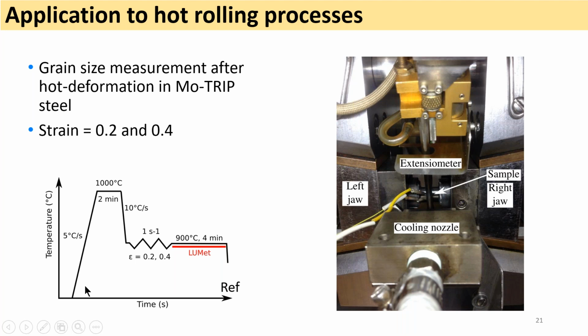This treatment consists of a sharp rise in temperature up to 1000 degrees, and then we lower the temperature to 900 degrees, apply a deformation of 20% or 40% strain, and then hold at 900 degrees for the recrystallization to occur. The picture that I show you here is the setup that we have used. There is a quenching nozzle here to quench the sample after the treatment, the thermocouple, the extensometer to measure the strain during deformation, and left behind is a spot in which the laser will be fired.